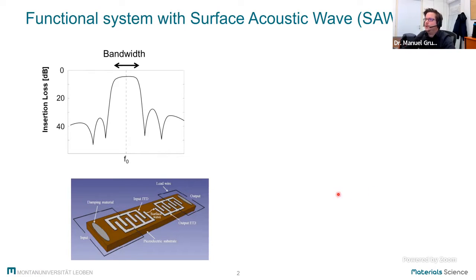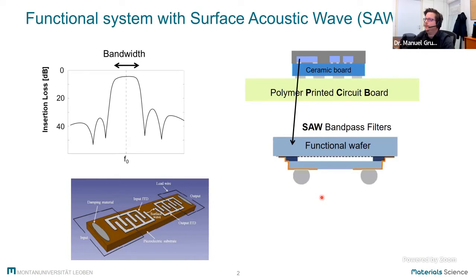So if we now have a look onto such a microelectronic system, we can see that our surface acoustic wave filters are on top of such microelectronic systems, and that the functional wafers consist of the single crystalline lithium tantalate and lithium niobate. And the electrodes are, you can see here, and very often there is a protective cap wafer to ensure that the very small metallic structures are not impacted by any kind of problems.